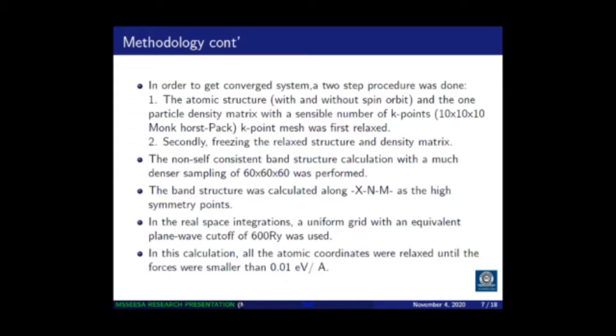Now the non-self-consistent band structure calculation with a much denser sampling of about 60 by 60 was performed without relaxing the system. There are some high symmetry points which are used in calculating the band structure in this case. And in real space integration, a uniform grid with an equivalent plane wave cutoff of about 600 Rydberg was used. I also relaxed the system until the forces were much smaller than 0.01 eV per angstrom.